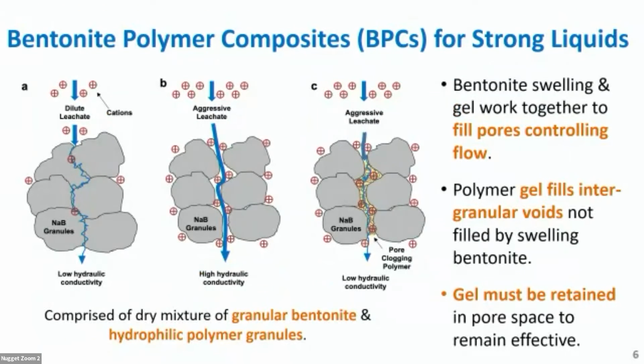So we were looking at materials that we could use or add to the bentonite to create something that would work under a broad range of geochemical conditions, from dilute monovalent solutions to concentrated divalent polyvalent solutions. And we stumbled on, actually by a mistake we made in our laboratory about 15 years ago, that by adding small amounts of hydrophilic polymer to the bentonite, we could actually create a composite material that would function over the entire range of conditions.